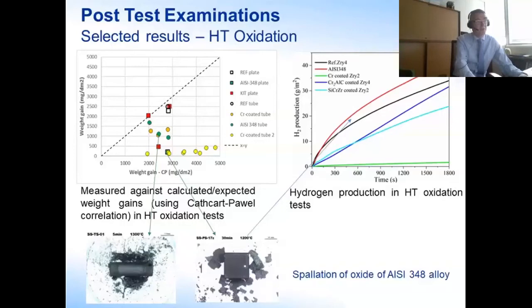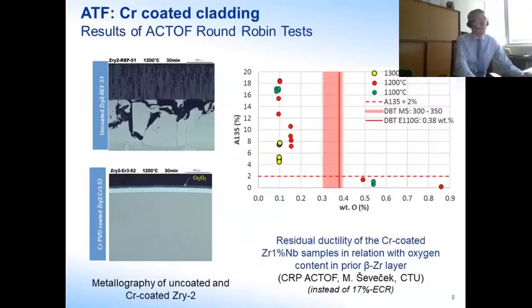And then you can see that the black line is the reference zirconium alloy cladding, so due to this spallation effect, oxidation of steel was very high, and then the others were better than standard Zircaloy, and again you can see the best behavior is chromium coated samples, and this is also shown on this picture. You see these are two samples, Zircaloy 2 without coating and with chromium coating, at 1200 centigrade for 30 minutes both, and here you can see oxide layer thickness, and chromium on the lower, which is much lower.